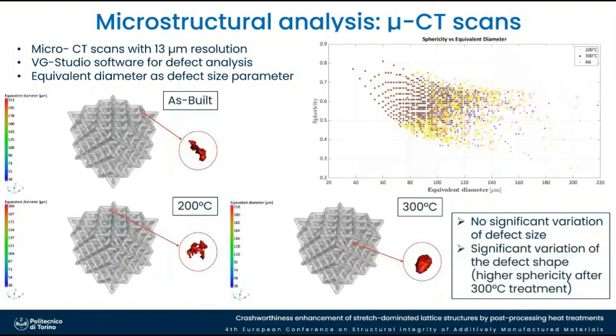While looking at the shape of the defects, we saw that in the as-built and the 200 degrees heat treatment, we have very non-spherical shapes, while at 300 degrees, we have more rounded defects. We are reporting the biggest defects that we identified in these three scanned specimens. So the heat treatment has an effect on the shape rather than on the size of the defects.